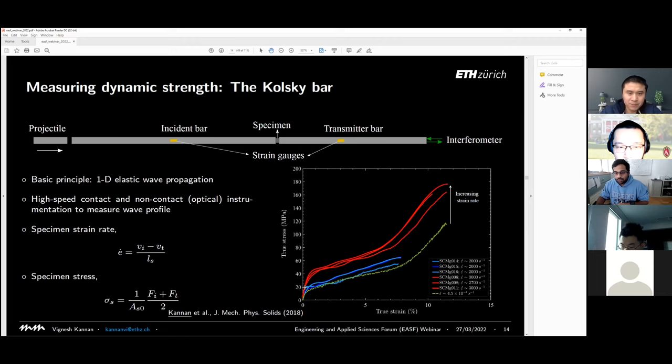And this could go up to really high strengths, because what happens here is when you reorient the crystal, you're applying load when the crystal orientation is along the direction of my left finger, and you switch the orientation because of the twinning, right? When you switch the orientation, you're now compressing along a harder orientation. So then the strengthening increases a lot. Okay. So that's why the strength is increasing significantly, but we're talking yields of the order of 20 to 40 megapascals. Okay, thank you.